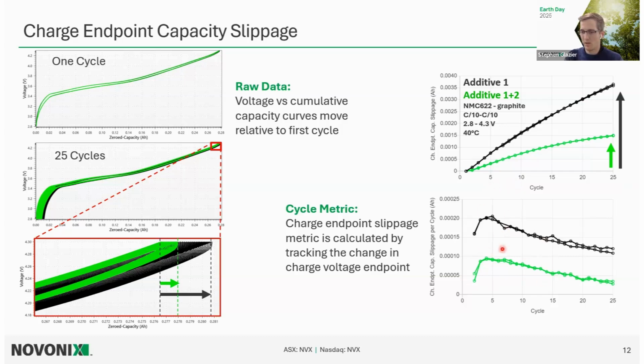And then showing down here just as a function of the amount of movement per cycle. So you can think about this as the rate of reactions. There's maybe 3 or 4 times the amount of these mechanisms happening without that propane sultone additive. So this is how we turn high precision data into these additional metrics and use them for analysis.